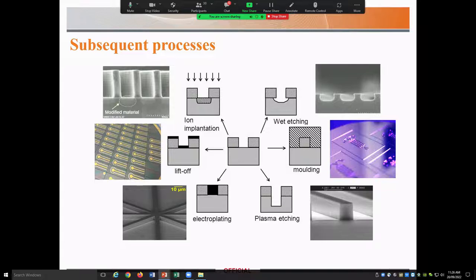Etching is removing the substrate material, and it can be done either in wet etching using chemicals such as acids, or in plasma etching, where we bombard the substrate with ions. There will be some lectures on these two technologies and techniques later in this microengineering school. In both of these etching processes, the photoresist can withstand the etching process and protect the covered area. So after the etching is done, we can strip off the photoresist from the surface, and we end up having the etched pattern in the surface.